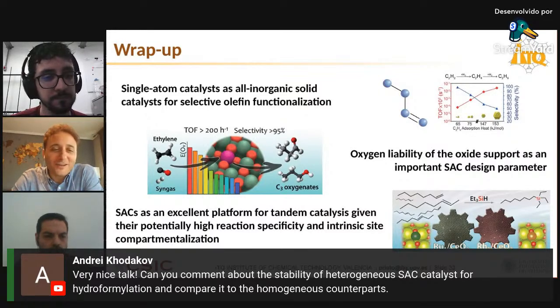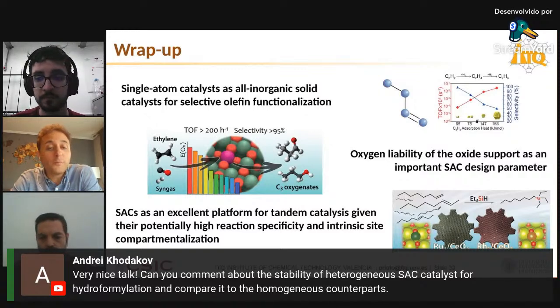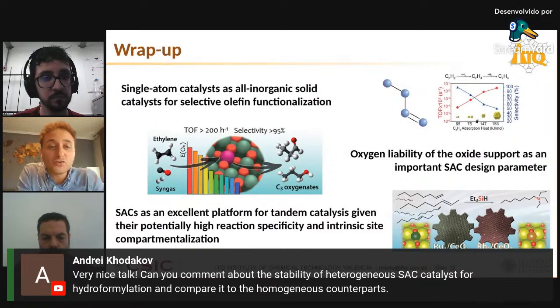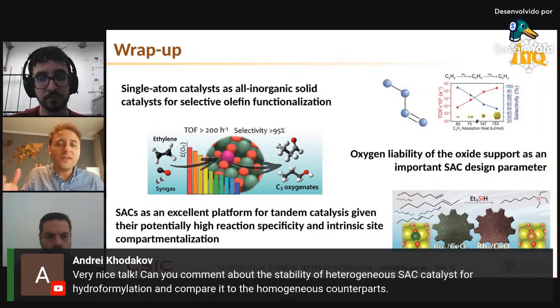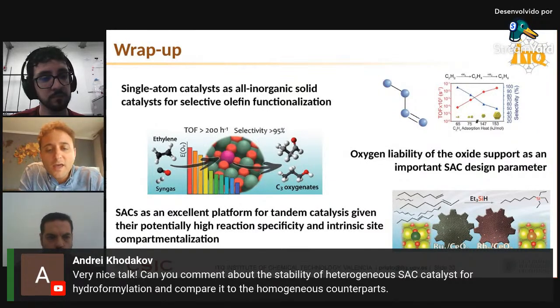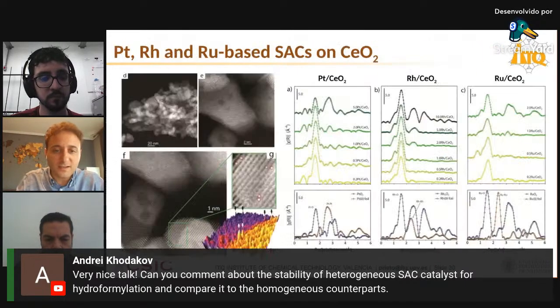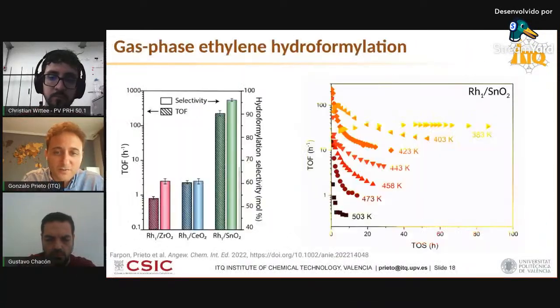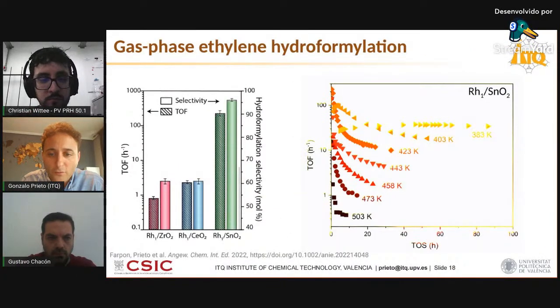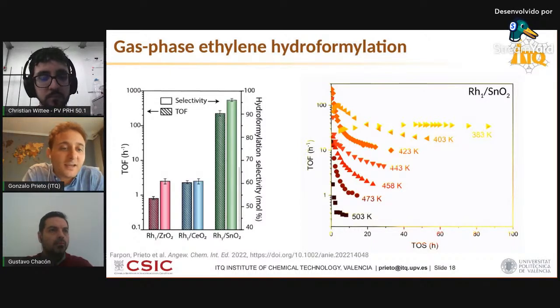Again, greetings to Andriy, and thanks for attending and for the question. It is difficult to compare because then we would need to compare homogeneous counterparts in liquid media and the heterogeneous ones, so the solid ones, in the gas phase. So that's already an unfair comparison to start with. The only thing I can say at the moment is that we could sustain the activity and the selectivity for our system. I think I was showing it at the optimized reaction temperature, we could sustain that, you can see here, for about 90 hours on stream. That's in a lab scale among the longest times that we have tested this system at.